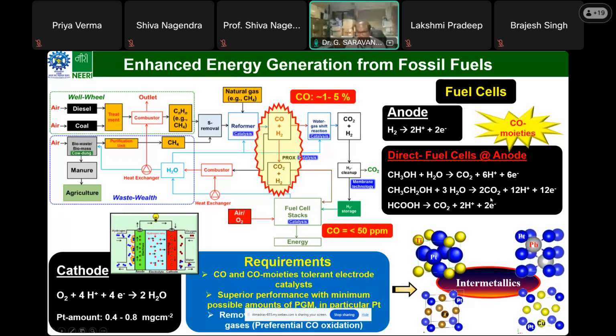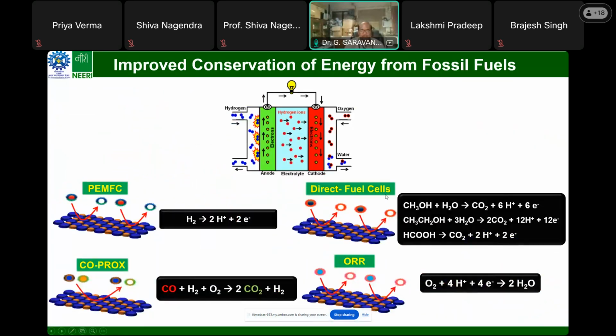Again, people are still using platinum as the catalytic center for both cathode and anode in the fuel cells, and because of certain limitations, as I pointed out earlier, we need to minimize the amount of platinum. So this is the typical hydrogen direct fuel cell. Among all these things, the oxygen reduction reaction is a very important step, which is a sluggish reaction, and it consumes a larger amount of platinum. So we need to minimize the amount of platinum here, and I'm going to discuss this one.